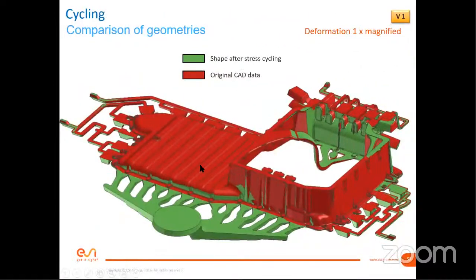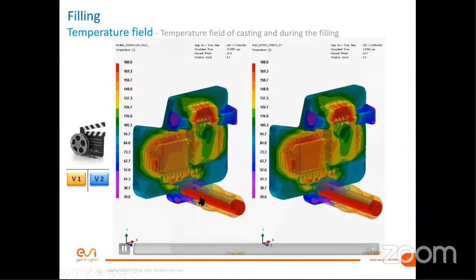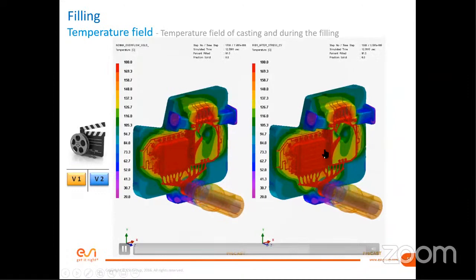After this calculation, from the 0 model of the casting, the new model was created, which also takes into account thermal expansion of the die. And this new model was used for the calculation of filling and solidification, like it is visible on the video. So we can see both variants, very similar from the filling point of view, but we can see how different they will be from the stress and deformation point of view.